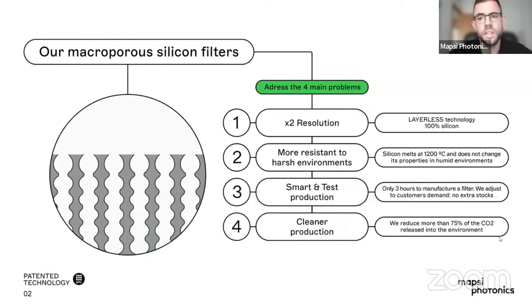controlling the shape of those holes, we are going to be able to, for example, increase some capabilities of the current technology. For instance, if we go above 5 microns, 6 microns, we can increase the resolution of the current technology because our technology is really intrinsically good at these wavelengths. We go from 5, 6 until 25 microns, for example.